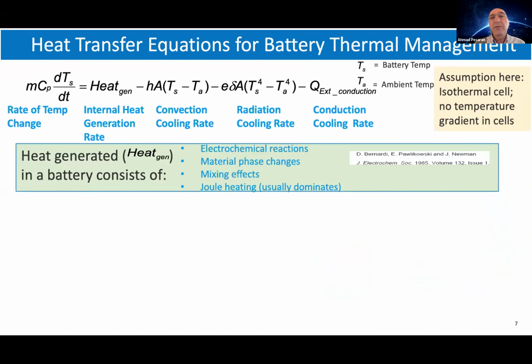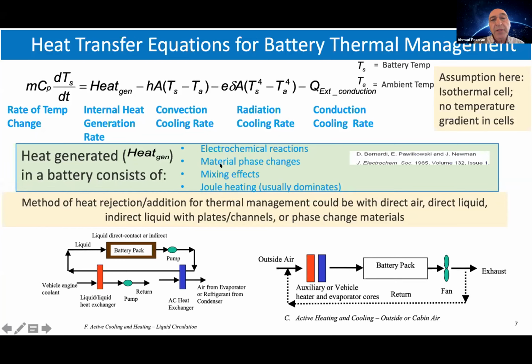But the basic heat transfer of thermal management is this: the temperature rise in the battery depends on the heat generation and the heat cooling rate, or, if you want to heat the battery, the heating rate. The heat generation comes from chemical reactions, material phase changes, mixing, and joule heating is the most important. At higher currents, joule heating becomes the dominant factor. The methods of heat rejection could be direct air, direct liquid cooling, indirect liquid with plates and channels and pins, and even phase change material.